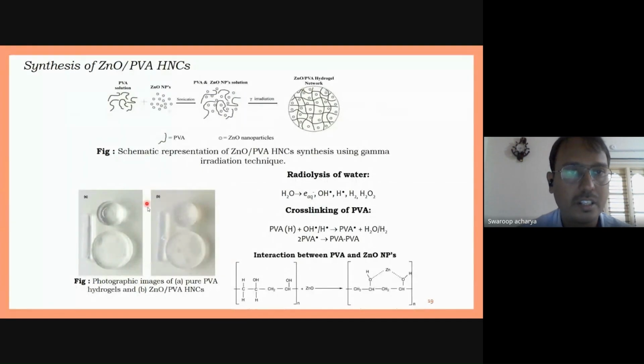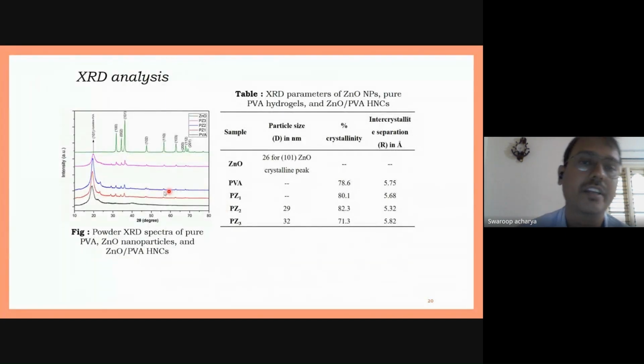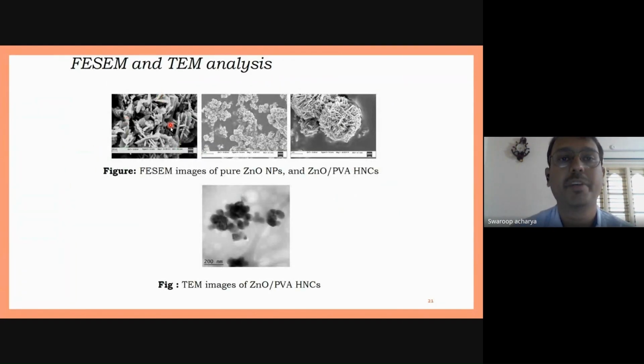So these are the hydrogels that we have prepared. These are the zinc oxide nanoparticles. These are the zinc oxide nanoparticle induced hydrogels, and these are the pure hydrogels. And this is the XRD result, which shows there is a trace of ZnO in the PVA hydrogels. And these are the FESEM images: this is the FESEM image of the pure zinc oxide, this is the hydrogel nanocomposite, and this is the TEM image.